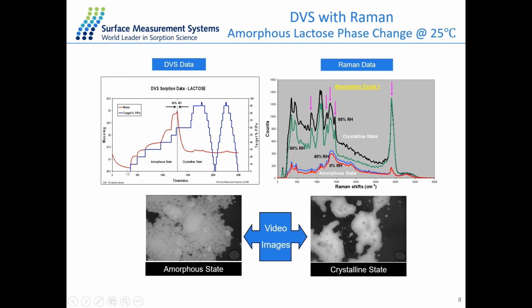So the sample is losing mass at the very beginning, just from the flow of the carrier gas for drying. And then it starts picking up the moisture and then reaches an equilibrium. Then it will jump to the next stage automatically. And at 60% RH here, you may notice that the mass is decreasing a lot, and this is due to the amorphous to crystalline phase change. And this phase change doesn't happen in the second cycle, so it's a kind of irreversible crystallization of the material. And this is some of the information we can get just from the DVS data.